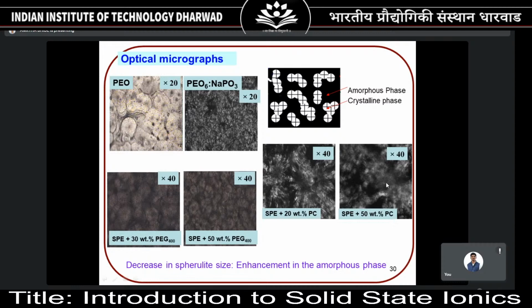And you had this enhancement in the amorphous phase, that is about roughly adding 50 weight percent of propylene carbonate. With this image, we could see the enhancement in the amorphous phase.